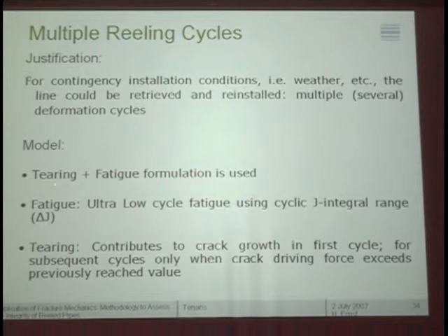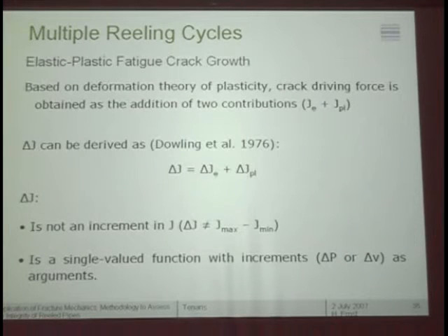So what we are going to do is simply follow the idea that some other people also use. That is a model that combines the tearing and fatigue formulation. And for the fatigue part, we are going to use the delta J range to calculate the crack extension due to that. Again, remember we are going to use also the idea that tearing contributes to crack extension in the first cycle only, except that if you see subsequent cycles, the crack driving force exceeds the previously reached value.